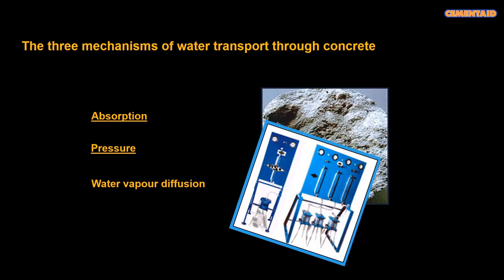It's interesting to look at which is the predominant mechanism of water movement through concrete. If I tell you that absorption probably accounts for up to a million times greater movement of water through concrete than pressure, you might be surprised at first. But as I said, pressure permeability really is a measure of the density of the concrete. What takes over is straightforward absorption. That is the predominant mechanism of water through concrete.